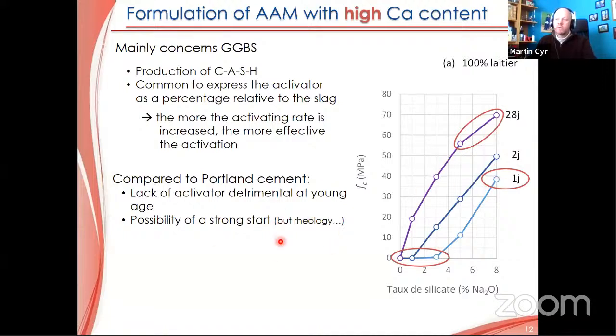So it's very nice to have this. But sometimes we have a lot of rheology problems if we are using slag alone with this kind of material. So that's the kind of thing we have to deal with when we work at an industrial level to implement this kind of technology on the market. The performance at 28 days could be as high as Portland cement, no doubt about it. We can see that we can reach up to 60 or even 70 MPa at 28 days, which is very interesting for this kind of material.